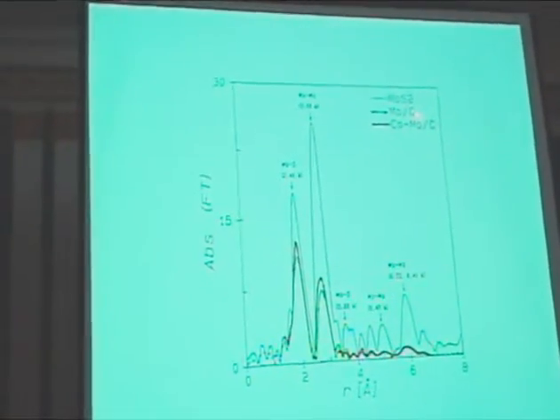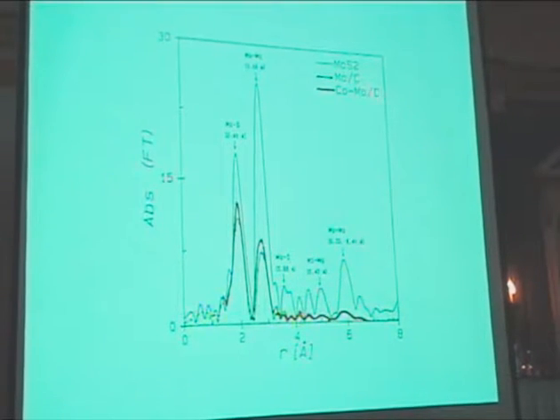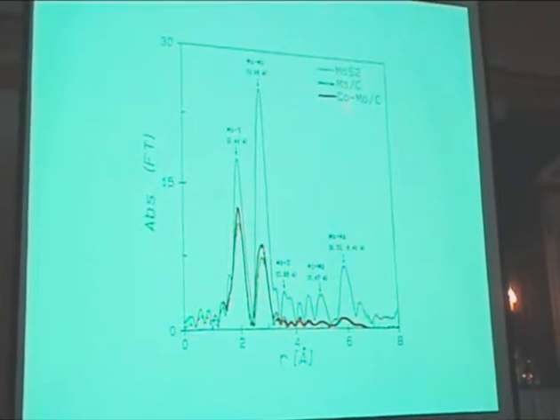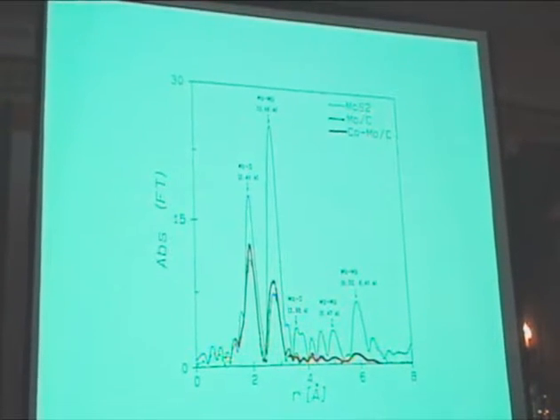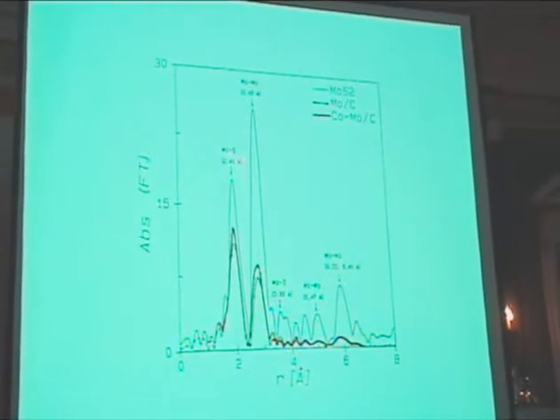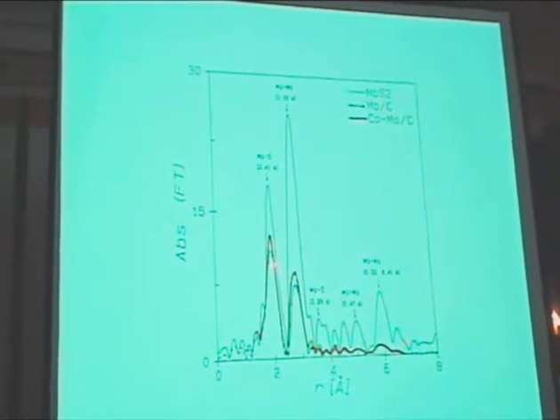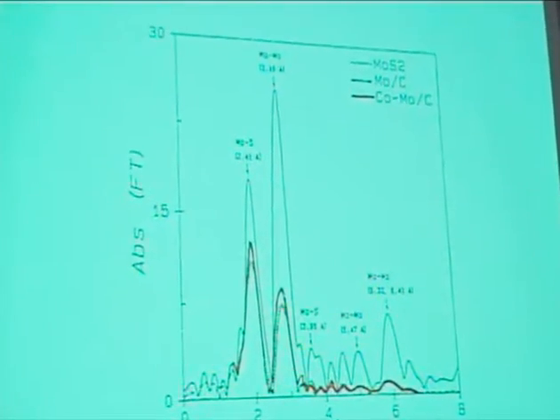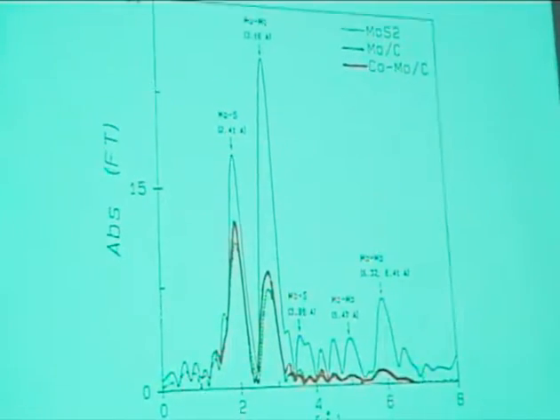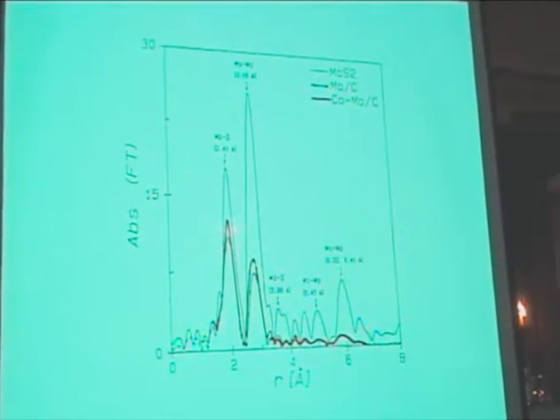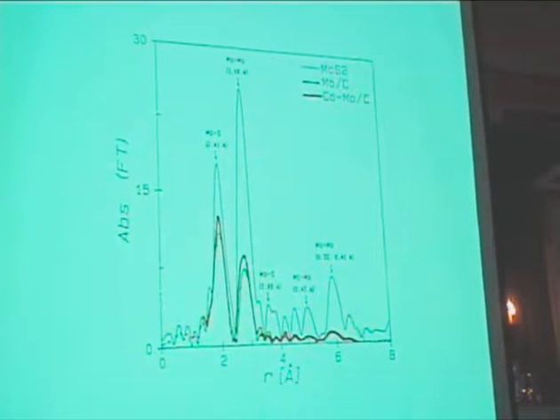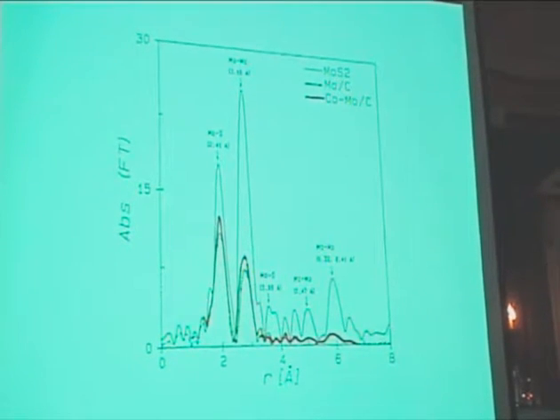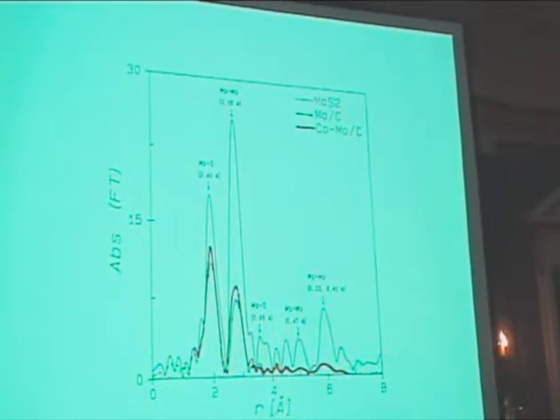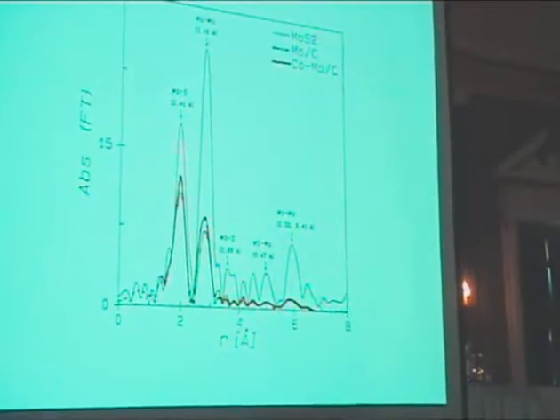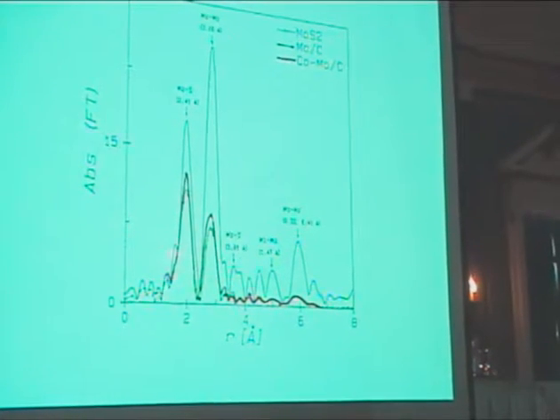Now, let's look at the catalyst. Well, we have done on carbon, we have done on alumina. Here I have an example on carbon, but it doesn't matter. It's a molybdenum disulfide and the one promoted with cobalt, where the nickel looks alike. The first thing to notice is that the first peak goes down in intensity. However, when you do the analysis, the number of neighbors is more or less the same. It's still around 6. It's a little bit lower, meaning that the atoms at the edges don't have the full 6, but they still have quite a few. And so the reason the peak intensity goes down is because of broadening. I'll come back to that.